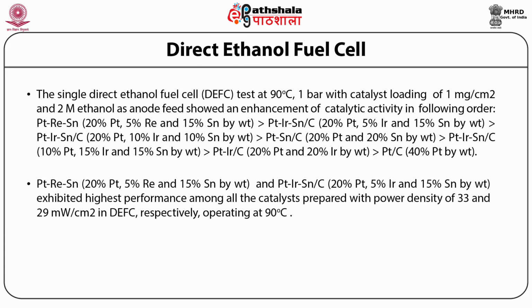Pt-Re-Sn and Pt-Ir-Sn over C exhibited the highest performance among all the catalysts prepared, with power density of 33 and 29 milliwatt per centimeter square in DEFC respectively, operating at 90 degrees Celsius.